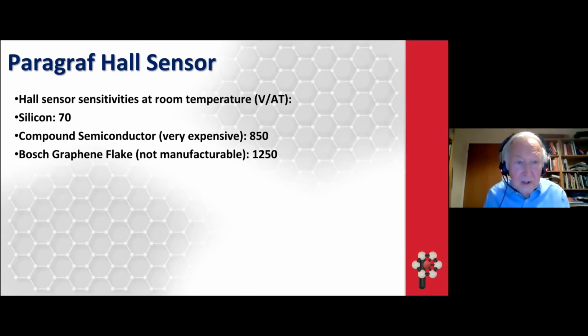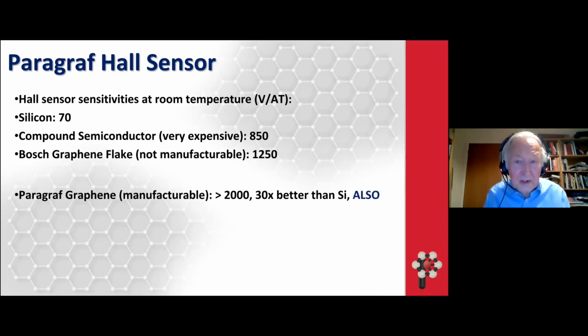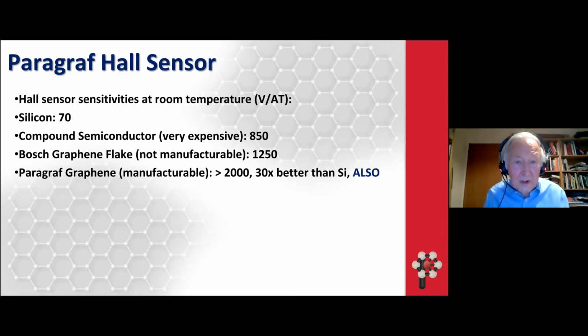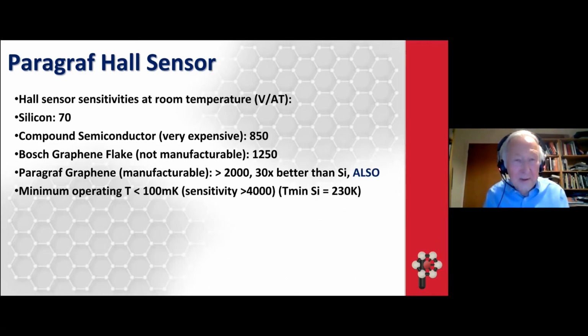But not only that, it will operate down at cryogenic temperatures. So the minimum temperature we found is about 100 millikelvin. That's the lowest we've got. We believe it will, as low as you can get, as you approach absolute zero, we believe our graphene Hall sensor will still be working. Not only that, it works better than at room temperature. So at these very low temperatures, the sensitivity is twice that at room temperature, 4,000 rather than 2,000. And Hall sensors like silicon, they don't work at cryogenic temperatures. The minimum temperature for Hall sensors to work is about 230 Kelvin. So it can do new things, not only do some things better than silicon, it actually is a cryo sensor, which other Hall sensors like silicon are not.